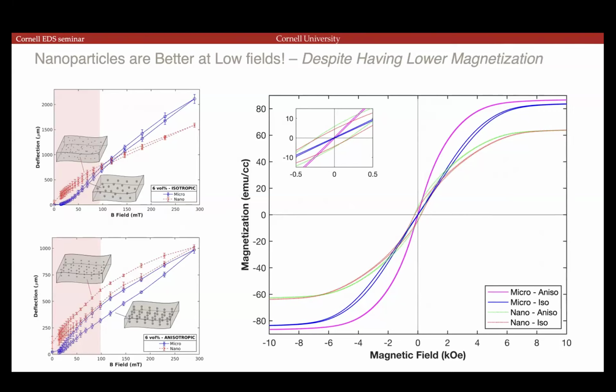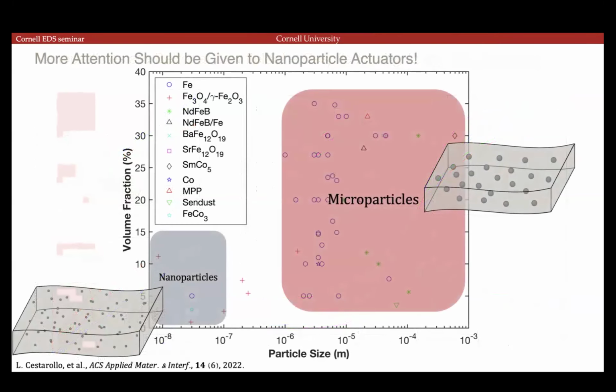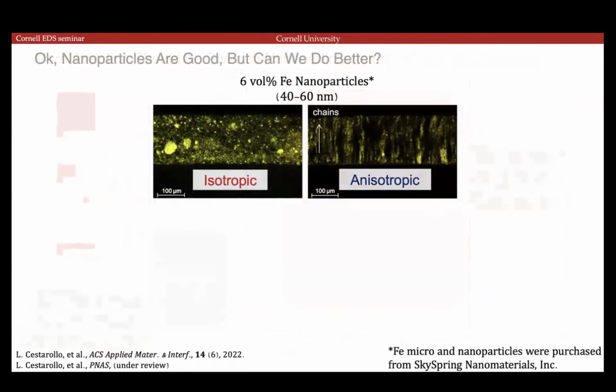So this is the feature that we want to keep improving in the nanoparticles. And how well do they actually maintain the magnetization as they're scaled down and as no magnetic field is applied. And again, like I said, we're trying to focus on fields that are below 100 millitesla because that's easily applied within an integrated system. So coming back to this picture, we compared the two, and it seems that the nanoparticle ones are better, so we can move in this direction.